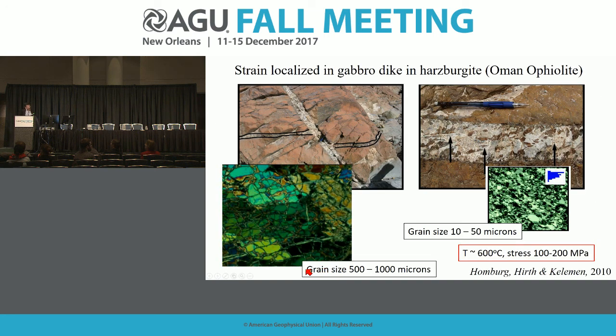So if we go to the ophiolites, we see lots of evidence for this. There are huge parts of the mantle where you don't find a lot of dikes, but there are other places where you do see gabbro dikes and also pyroxenite dikes. And here's an example of a cool feature that we found in Oman with these gabbro-norite dikes in peridotite, but you can see that there was deformation accommodated within the gabbro-norite.